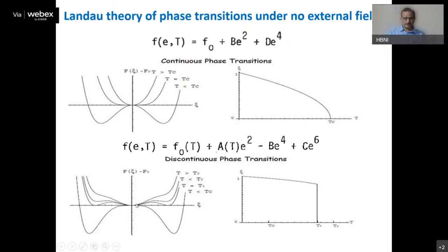You can clearly see in this plot that as the temperature decreases, you start getting one local minimum here. The energy is still higher up to this temperature. But at this temperature, T equal to some T0, T equal to some Tc, this basically has three stable equilibrium positions, the critical point. And then at subsequently lower temperatures, you start getting the non-zero order parameter arising discontinuously. Now let us see what happens when we introduce an external field.